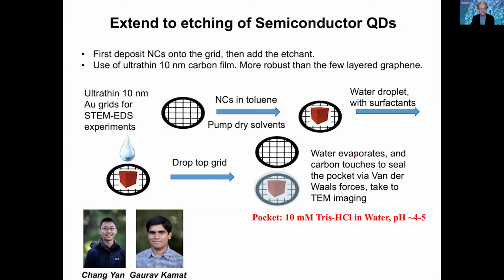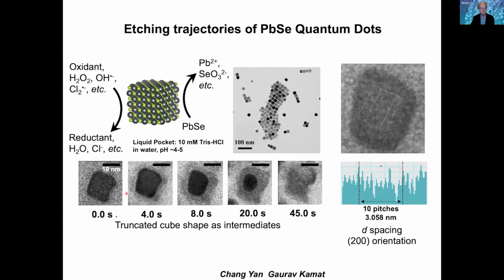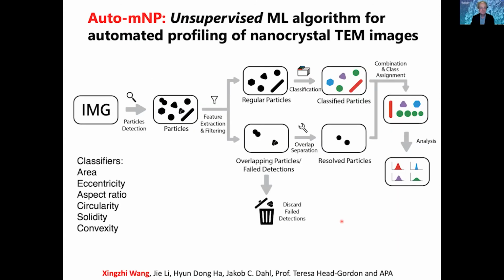Chang Yan and Gaurav Kamat have been working for a while now to develop the right conditions for doing that. There are some tricks to it. It's not one of the easier experiments, but we do have it working pretty consistently now. I'm not showing any movies here, but we have developed a very large set of etching experiments on these lead selenide nanocrystals in which we're able to set the chemical potential inside the liquid cell sufficiently low that we can observe the trajectory of etching of this very sensitive species. Two or three years ago, we'd put these things in there and they would just be gone before you had a moment to even look at them. So we're getting closer and closer to being able to turn up or down the oxidation potential in the liquid cell.